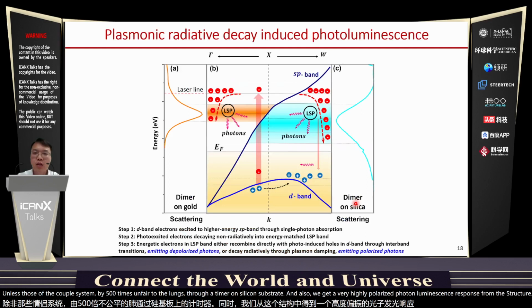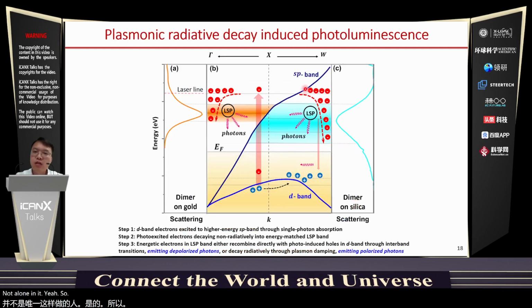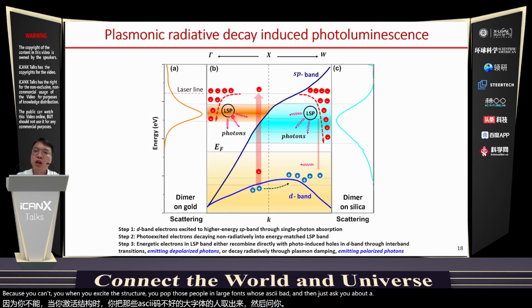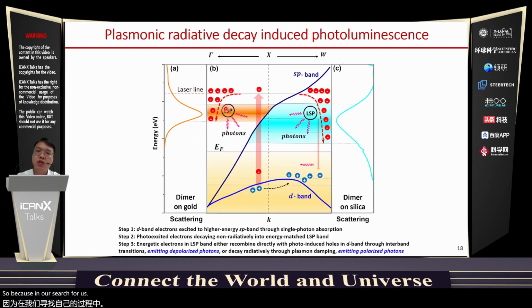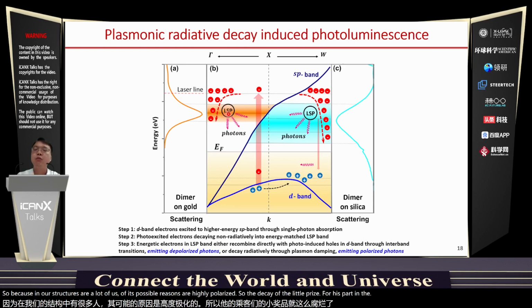Yeah, this phenomenon can be easily explained because when you excite the plasmonic structures, you pump the d band electrons to the sp band, and then this sp band can couple with your localized surface plasmon resonance. Because in our structures the localized surface plasmon resonances are highly polarized, the radiative decay of those localized surface plasmons will also give you a highly polarized photoluminescence signal.